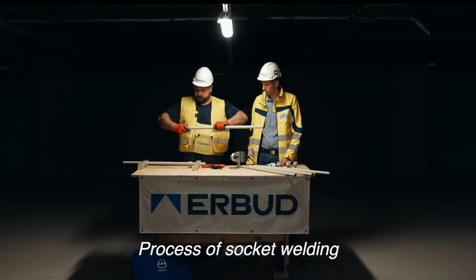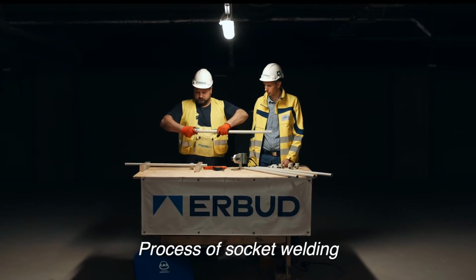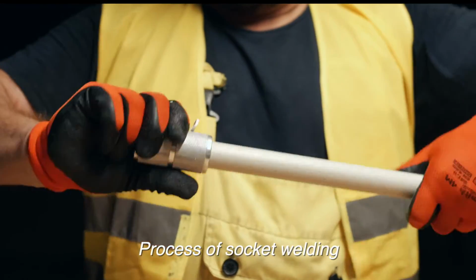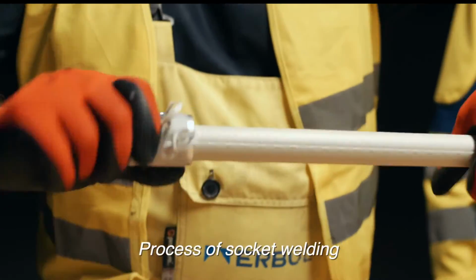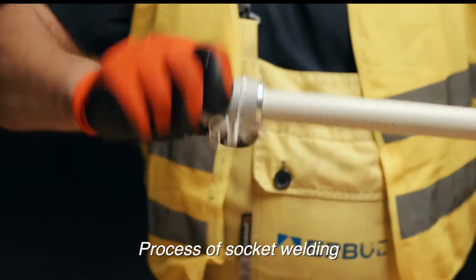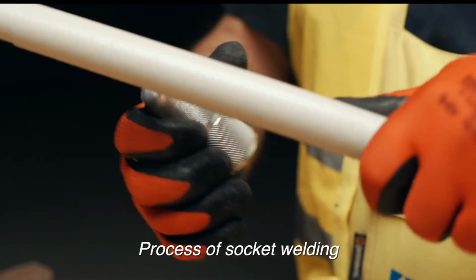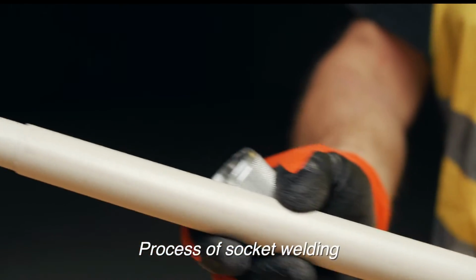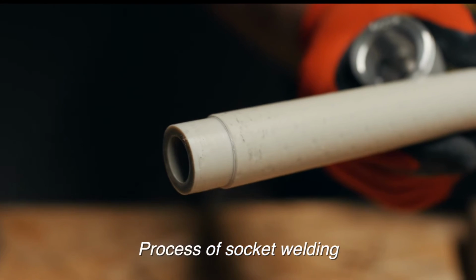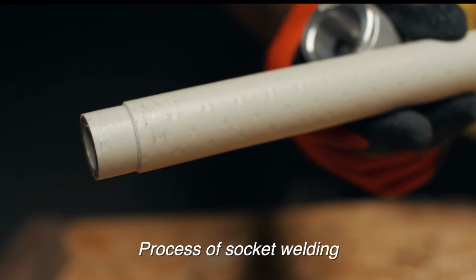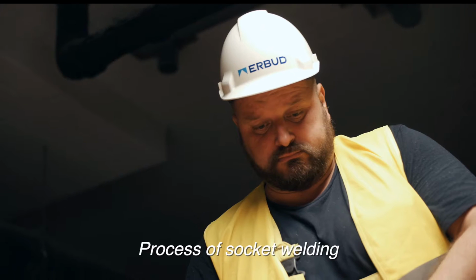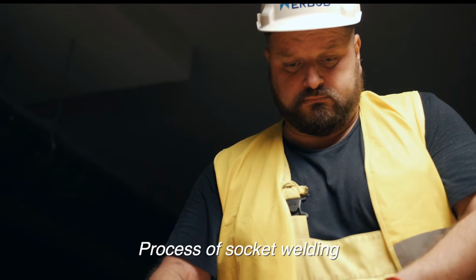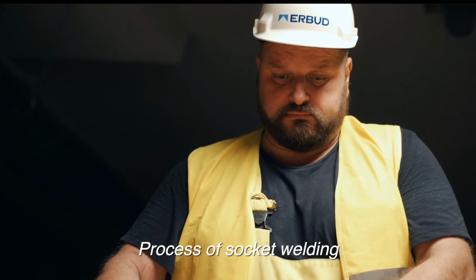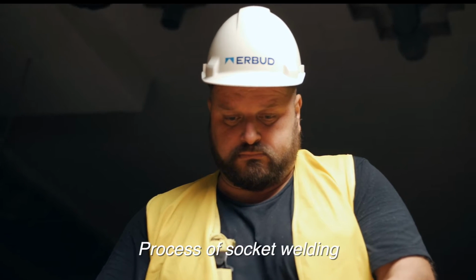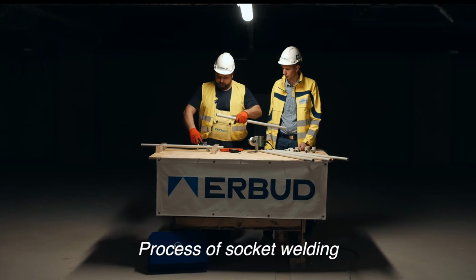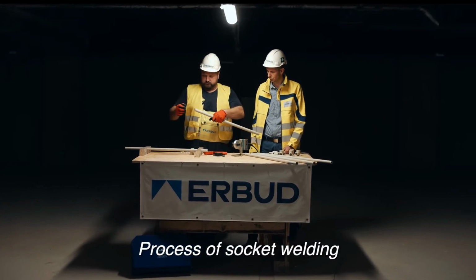On this side of the pipe, insert the stabi pipe into the peeling tool to remove the composite aluminum layer with a twisting motion. You will see debris from the cutting. The length of the section with the removed aluminum foil determines also the welding depth. Always check that the work area is free from residues of aluminum or the binding layer. Cutting blades must not be blunt or chipped. Replace worn blades with new ones.